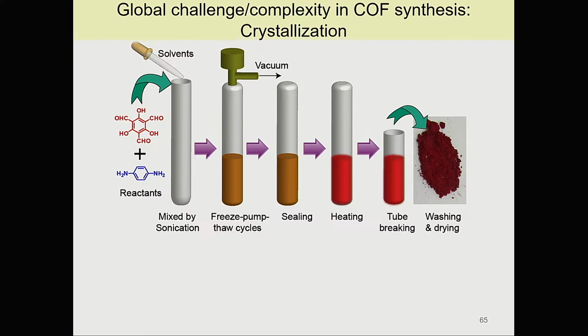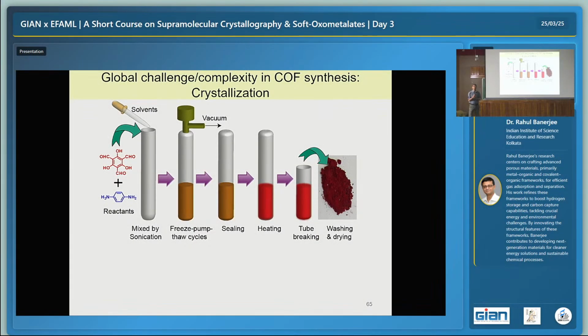Then you take that and put it inside an oven at 120 degrees centigrade for 7 days. So what will happen? At 120 degrees centigrade, this will try to go out, evaporate. It can't because it is flame sealed. So it will give back pressure. Now what is the problem? At higher temperature, solubility increases. As you increase the temperature, solubility increases. At higher pressure, solubility decreases. So in this process of tug of war, you will eventually make this thermodynamic structure we are talking about, if you are lucky, on a very lucky day, 50 to 100 milligrams.